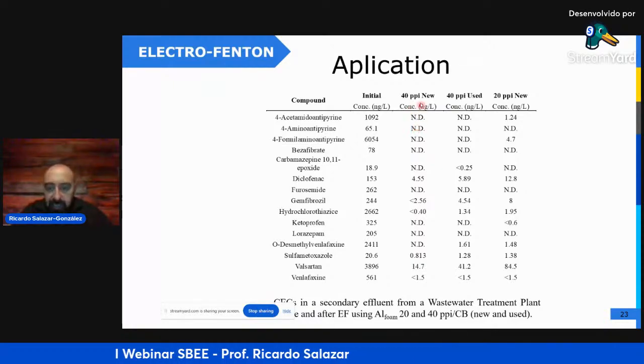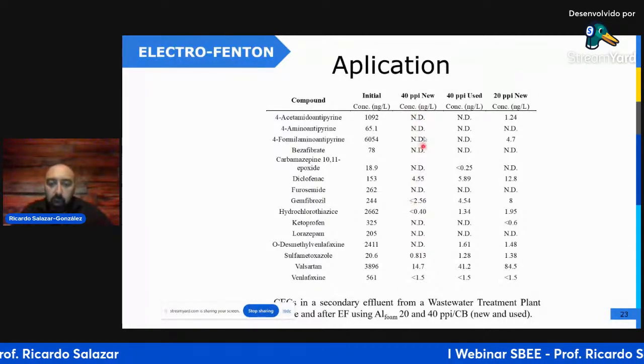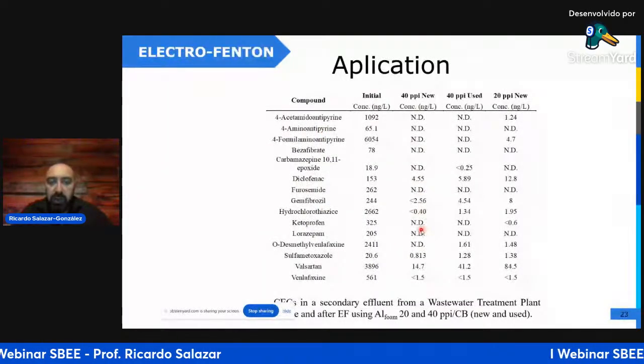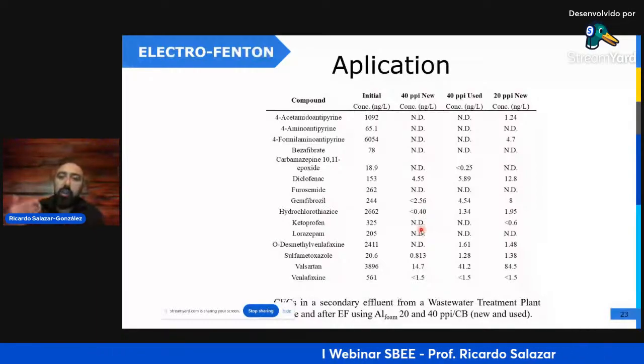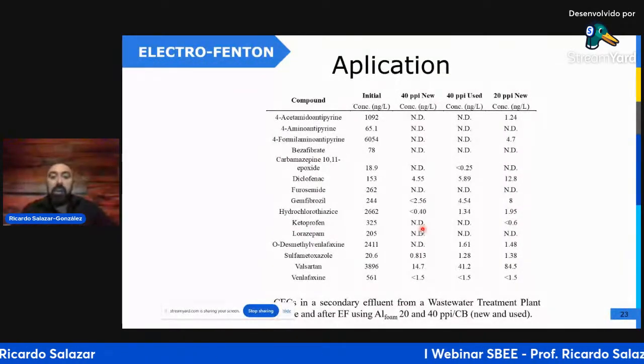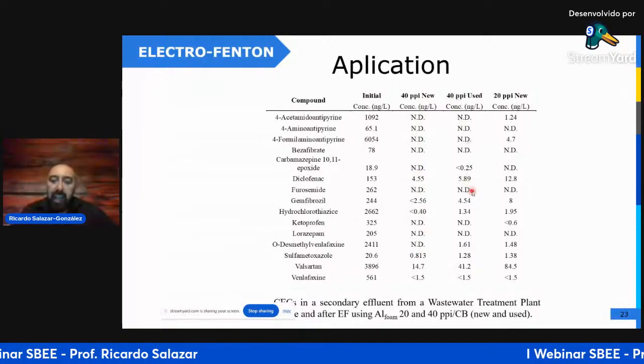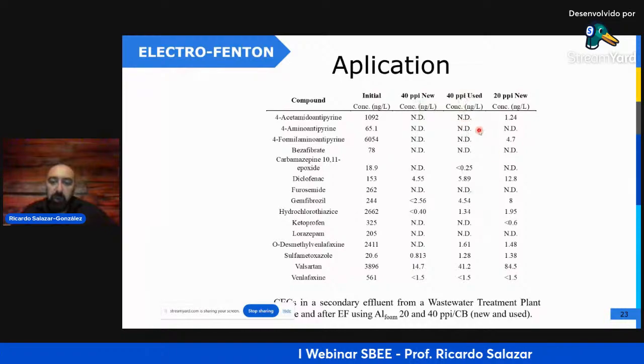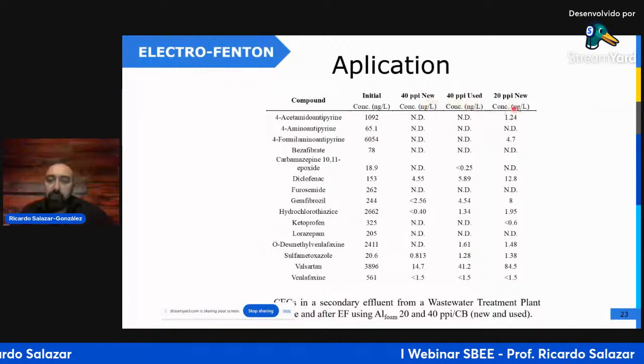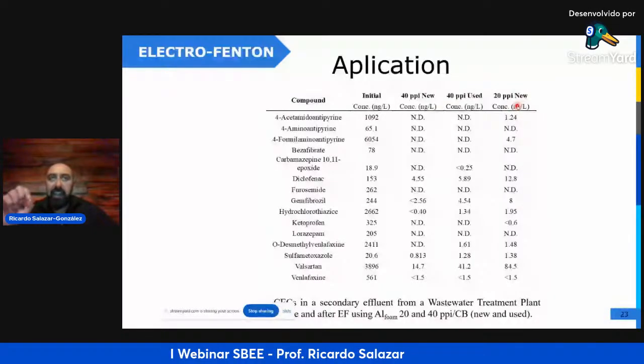And when we apply it, after 30 minutes of electrolysis, we reach almost the complete elimination of almost all pollutants present in the real wastewater. This was without the addition of supporting electrolyte. We used the real wastewater without any change, applying our system for the production of hydrogen peroxide. And the electrode was used multiple times, and you can see that the same electrode produced almost the total elimination of the pollutants. And we produced different aluminum electrodes modified with carbon black with different pore sizes, and the performance was very similar.